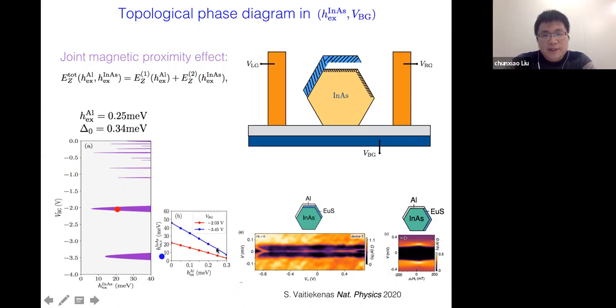So this numerical simulation shows that it is indeed more favorable to have an overlapping geometry, because it has 2 sources of Zeeman, while this one can only rely on the direct effect, which needs to be very, very strong. So this is how we understand this geometry difference between the two devices, and have an estimate about the possibility of realizing topological superconductor in this ferromagnetic hybrid nanowire.